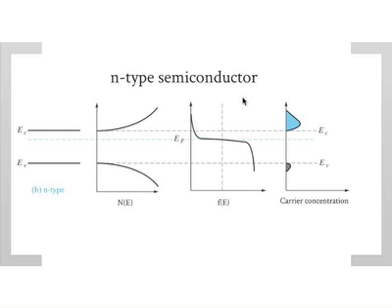Of course, the Fermi-Dirac distribution just moves up a little bit. Otherwise, it's the same. The shape doesn't change. You multiply them together, do an integration. Of course, because this has moved up, the probability here has increased. So, of course, you get many more electrons here. And fewer holes, because the probability here has decreased in terms of holes.